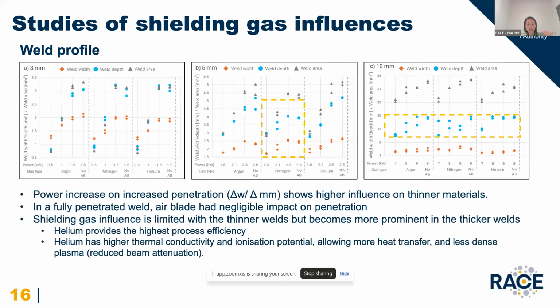The relationship actually shows a higher influence on thinner material. You can see that the generation of the depth is steeper. And then on the 16 millimeter, for helium, it reached full penetration at a fairly low power of 8-9. They will generate similar results.